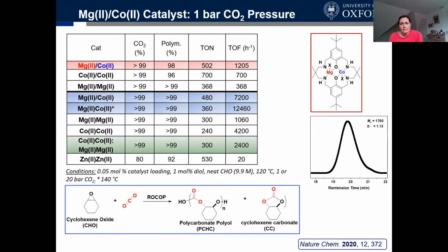So now what I'm going to do is compare for you some of this activity data under a few different conditions. I don't want to bombard you with too many tables, but at the top is the data you've already seen. In blue is data that's collected at higher pressure. And what's happening in these higher pressure runs is you see quite a big leap in activity. The bottom one is at higher temperature, 20 degrees higher than the one above it. And of course, we get a higher rate with higher temperature.